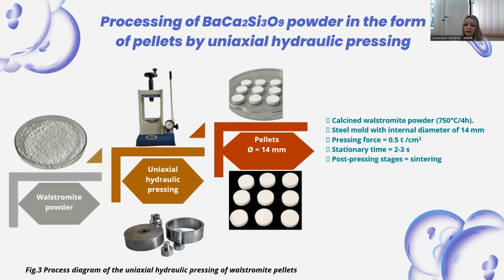So I used the calcined powder, which I pressed using a uniaxial hydraulic press with a steel mold with an internal diameter of 14 millimeters, a pressing force of 0.5 tons per square centimeter, and a stationary time of 2-3 seconds. We obtained a lot of pellets that you can see in the images, and with them, we moved forward to